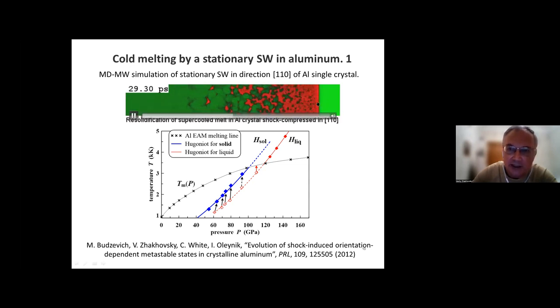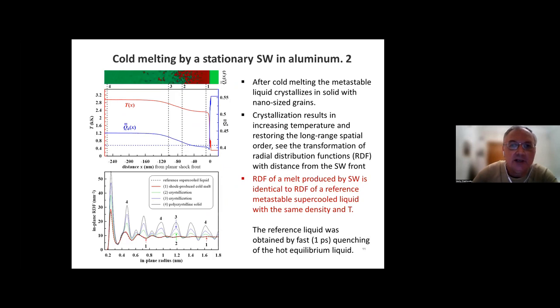So the initial state, just immediately after the shock front, is a metastable liquid, and it is placed on the liquid branch of the Hugoniot. And then it slowly transforms in the aftershock flow to the thermodynamically stable solid state, which lies on the solid branch of the Hugoniot. So crystallization also results in restoring the atomic order parameter in the aftershock flow and an increase of the temperature. It's simply because of the release of latent heat due to crystallization. So we also observe transformation of the radial distribution function, and the recovery of long-range order in the positions of atoms is clearly visible here with the distance on this plane from the shock front.